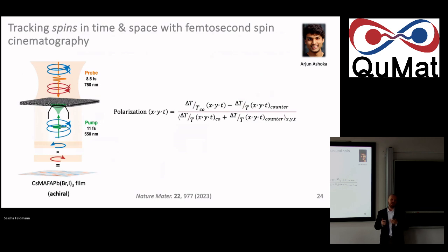But in the end, we arrived at a circular polarized pump probe microscope, having diffraction-limited spatial resolution, actually a little bit better than that, and then importantly 15 femtosecond time resolution, and being again able to look at co and counter-polarized handedness. So what I plot now in the next step is the mapping of such a pump probe experiment of a film of a halide perovskite. It's this one cesium MAFA iodide bromide. It's just a very well-known composition that works well and is rather stable. And I'll plot, for simplicity, just the green curve, so to say. So I'll plot co minus counter of the TA perovskite bleach and divide it by the sum of the signals. So just net polarization response.